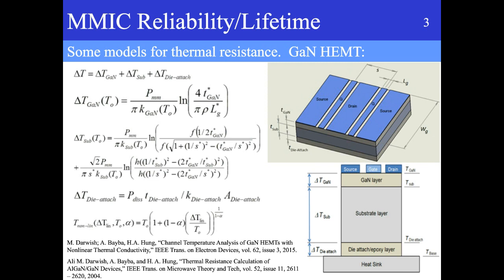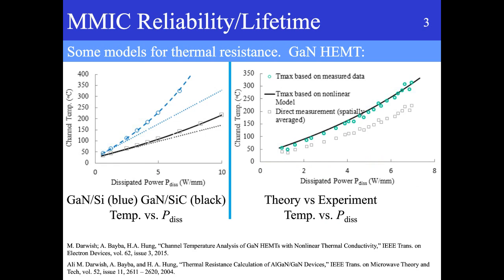And if you would like to be accurate, you would need to consider the die attach because the temperature rise across the epoxy is significant. And so this slide shows this calculation for gallium nitride. And in addition, it shows how you would take the nonlinearity of the thermal conductivity into account. And this is especially important for devices that will have significant power. So for example, if you look at the graphs here, you look at the channel temperature on the left, and the dissipated power. This is for gallium nitride on silicon, the blue line, and gallium nitride on silicon carbide.